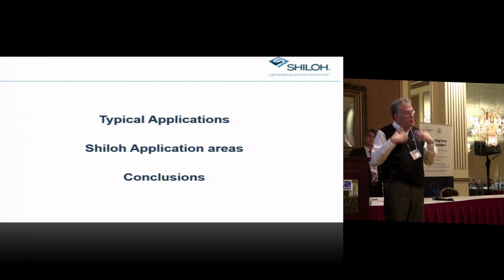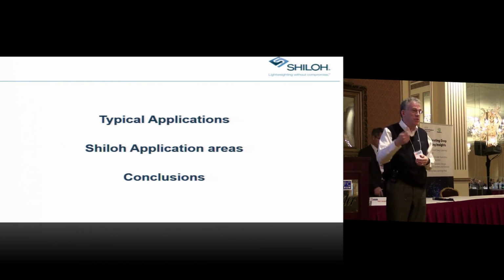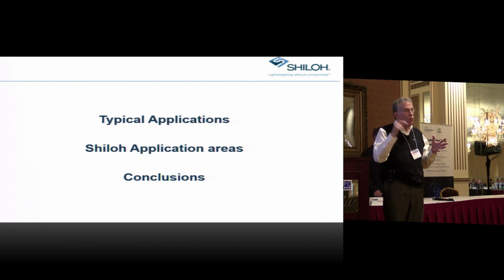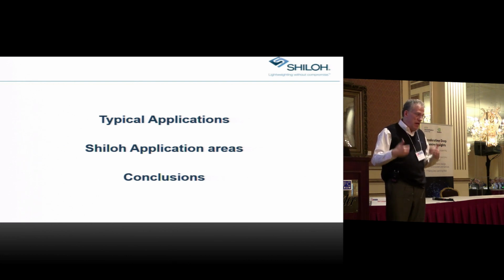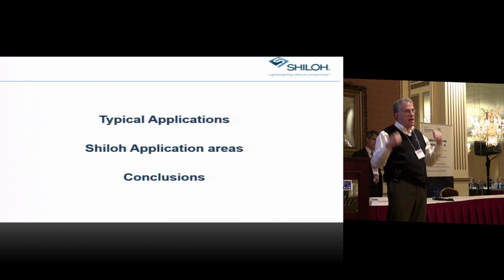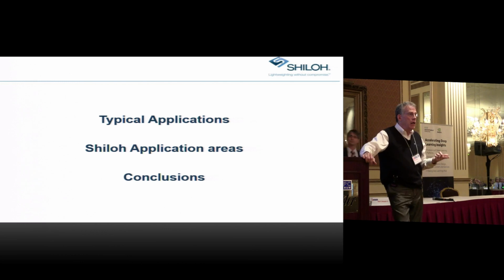So if you have a cavity that's rather expensive, that means you're replacing that cavity every 100,000 cycles. Now, if I can get 15 or 20% greater life out of that same cavity set, which I can do if I'm optimizing the cooling, cost to the customer goes down. So that's one element. Another element is just the resources used that are reduced, and that's everywhere. That's the heating of the metal, the casting, taking the die out, changing everything. It's all that wasted effort, it's waste that we need to eliminate. It's not something that adds value to the customer.